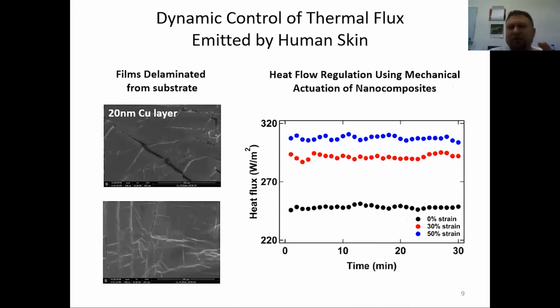So, in terms of the amount of heat flow regulation by mechanical actuation, in the initial unstretched state, the nanocomposite material maintains a steady heat flux from the hot plate with an average value of about 250 watts per square meter. As we mechanically actuate the nanocomposite material, the steady state heat flux from the hot plate increases up to about 310 watts per square meter for a mechanical strain of 50%. So basically, these measurements demonstrated that the nanocomposites manage up to 70% of the metabolic heat generation, which is about 75 watts per square meter for resting individuals or sedentary individuals at the office.